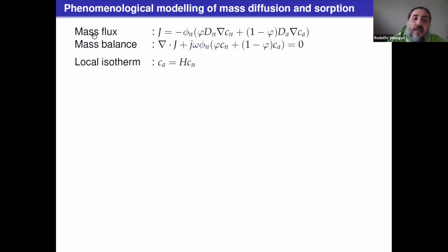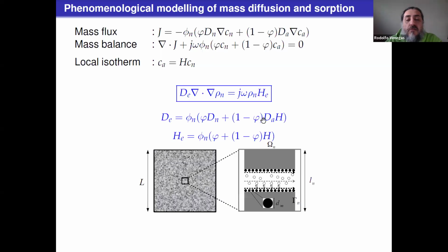So in terms of modeling, we have a mass flux that has two contributions, one coming from adsorbed molecules and the other from, let's say, free molecules. If we do a mass balance, we get this equation, and we need the relationship between the adsorbed molecules and the free molecules, which we consider through a local isotherm where H is a proportionality constant. So combining all of these equations, we get this diffusion equation where D is an effective diffusion coefficient and H is an effective sorption equilibrium constant that depends on the volume fraction of the system available for the free molecules to diffuse through. It depends on the nanoporosity of the material, and also on two different diffusion coefficients. One of them is the bulk diffusion coefficient, and the other one is the surface diffusion coefficient.